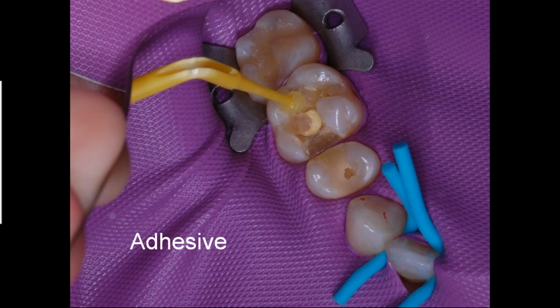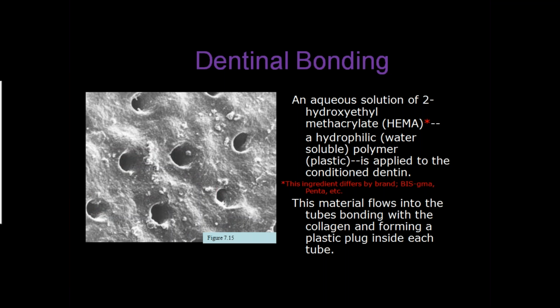So first thing we do after we remove the old composite is we're going to start with our adhesive step. And I'll show you, as in later cases too, the following recommendations of a selective etch is certainly the way to go, and these self-etch adhesives are also the way to go, eliminating really post-operative sensitivity, reducing protease enzyme creation for breakdown, micro leakage down the road, and really something which is much more predictable because of the nature of being more forgiving as far as moisture content. Too desiccated or a little bit too much moisture really doesn't matter with the bond strength. So we're going to go ahead and scrub this in the tooth for 20 seconds. We're going to go ahead and air dry it for about 10 seconds or so.